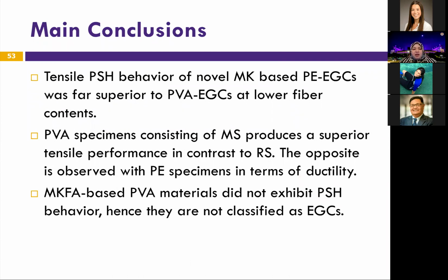The tensile pseudo-strain hardening behavior of metakaolin-based polyethylene and PVA EGCs was superior to the PVA EGCs, but they both worked. The PVA specimens consisting of microsilica sand produced a superior tensile strength to that of the river sand. The opposite was observed with the polyethylene specimens in terms of ductility. The metakaolin fly ash did not work. It did not produce pseudo-strain hardening behavior, so we cannot classify it as EGC, but we're going to work on that.